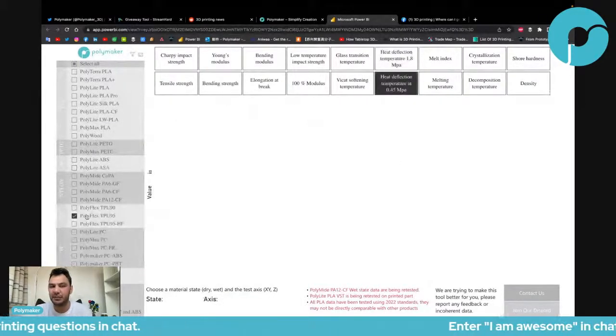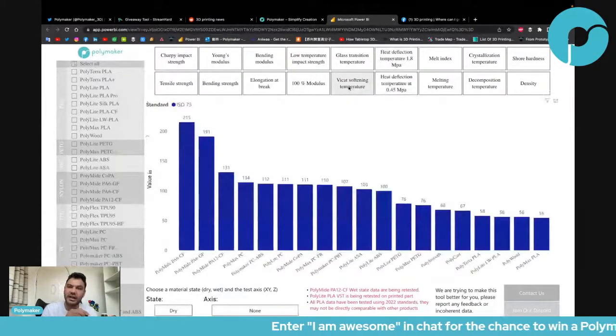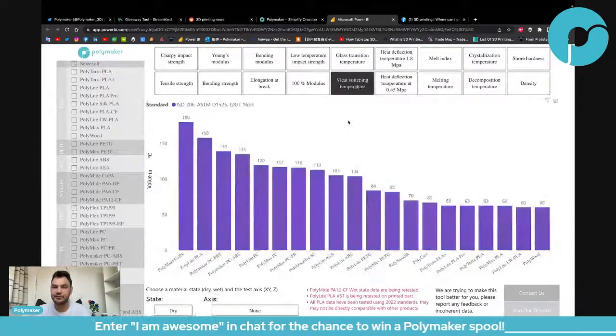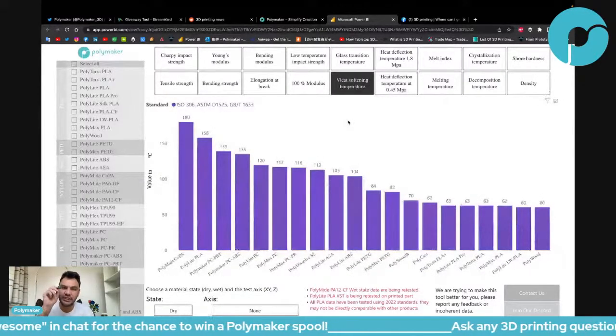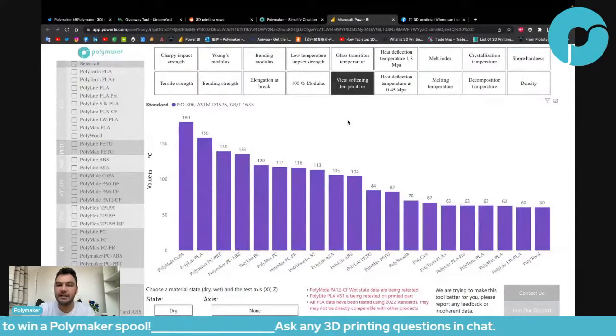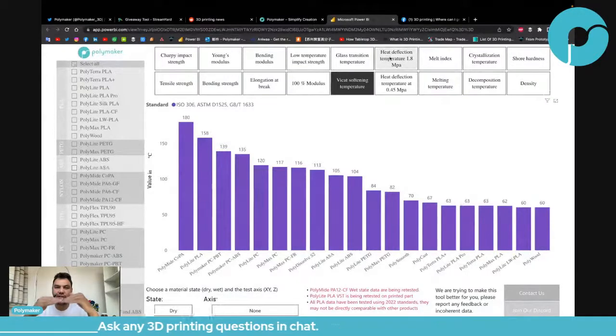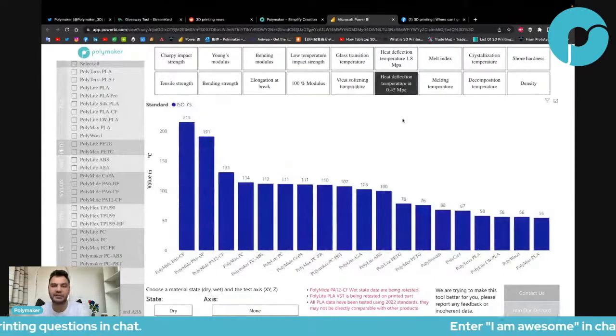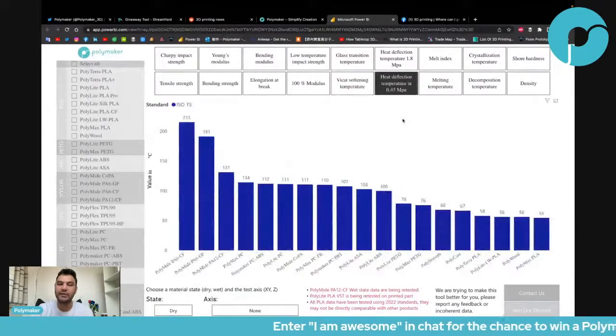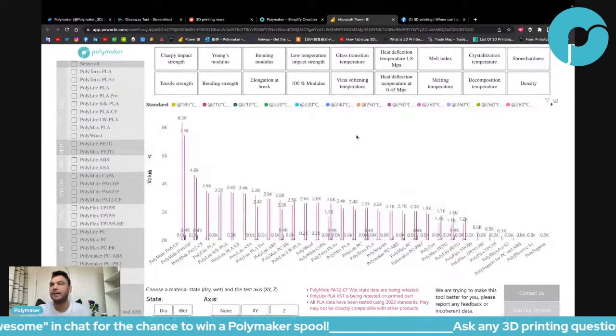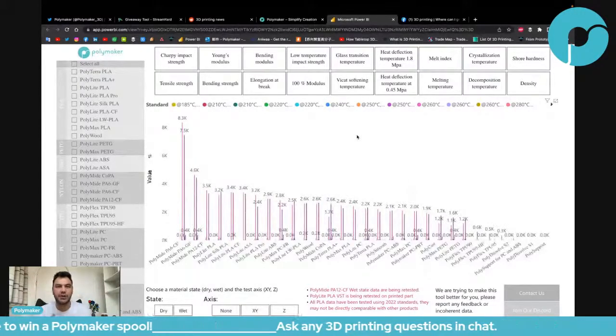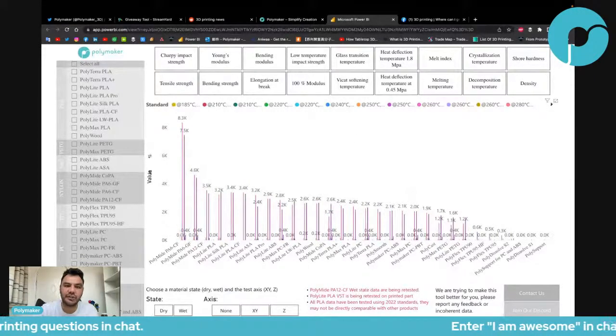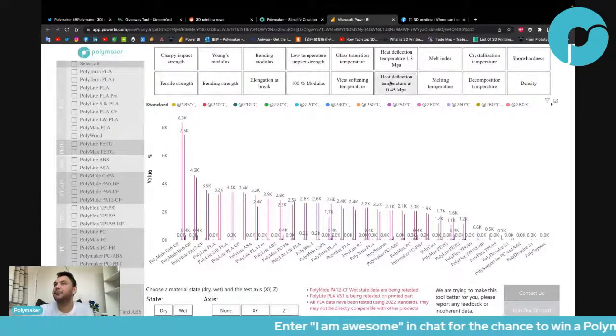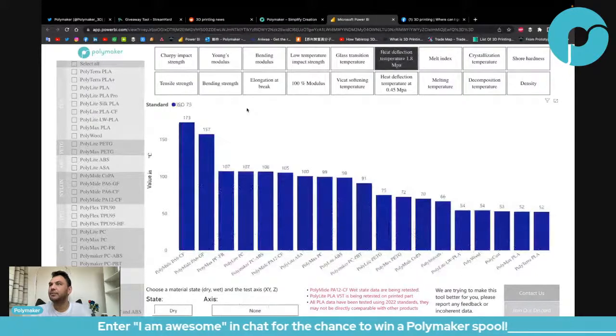And that's how we define heat resistance. You have either the Vicat softening temperature, which means the actual softness of the material: at which temperature does it become soft, at which temperature can you push a needle inside. And the HDT is at which temperature does it start to deform more than a certain amount with a certain amount of stress. So when you ask whether something is heat resistant or not, you have to define what type of heat resistance you are talking about. And then there are all of these questions around creep, right? Creep issues or temperature creep deformation. This is also important to know. Okay, so that was the question from Matt.